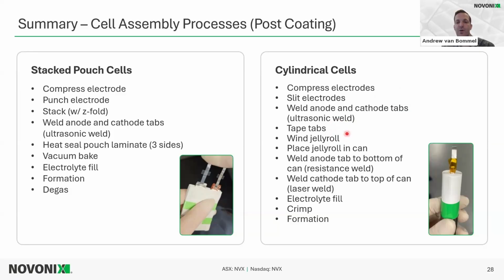The jelly roll is wound. So this would be those 4 layers: separator, anode, separator, cathode. That jelly roll is placed in the can. The mandrel is put down into the jelly roll, and the anode tab is welded to the bottom of the can with a resistance weld. And the cathode tab has to be welded to the top of the can, or to the header, with a laser weld. And after that, they're also vacuum baked, and there's enough electrolyte fill. The cells are crimped and formation is done. In this case, there's no degas for our typical projects.